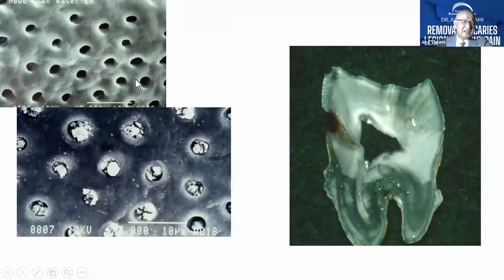And this is the SEM after the phosphoric acid etching. The beautiful etching pattern is observed, but this is the intact dentin surface. And this is the caries affected dentin surface after the phosphoric acid etching. Even after the very strong etching, the tubules were very well occluded by the mineral deposit. This is a very excellent defense system of the tooth against the caries attack.